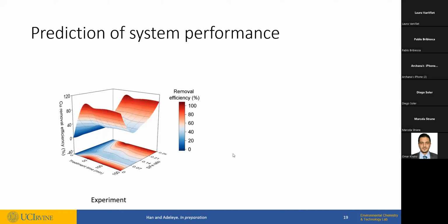So we went ahead and confirmed how well the function we developed worked. Here is a plot made from experimental data showing the efficiency of copper removal based on treatment time and S/Fe ratio. Every other factor held constant. And at the bottom is just a reflection of the 3D graph. So when the treatment time is 0, there's really no removal. But as you have more treatment, you have more removal. And intermediate S/Fe ratio particles don't perform as good as NZVI. And when the sulfur ratio is as high as 0.28 molar ratio.